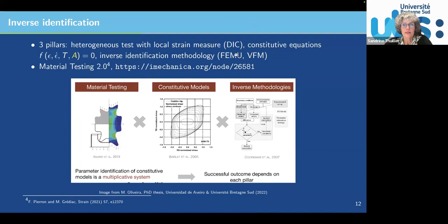So this is finite element model updating, and maybe I did not stress enough the fact that you need a local strain measure for your experiments. So using digital image correlation in order to capture the whole strain field. So you've got this material testing with DIC, you've got your model, so the mechanical model, and with the inverse methodology, let's say FEMU, then with these three methods, you will be able to determine the best, or at least a very good, material parameter.